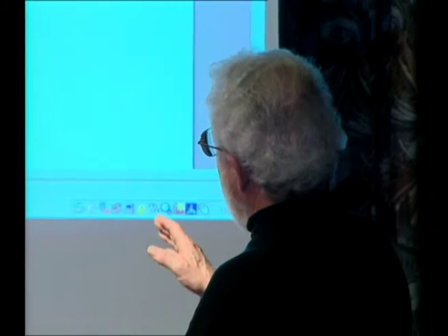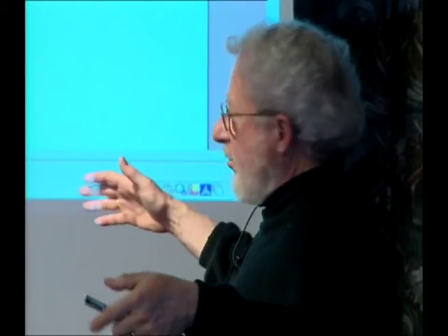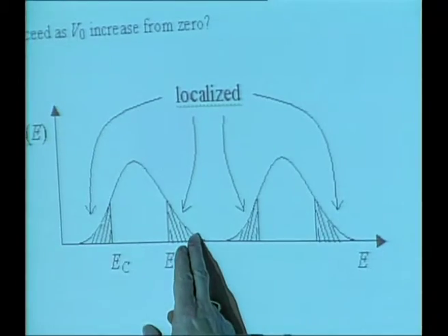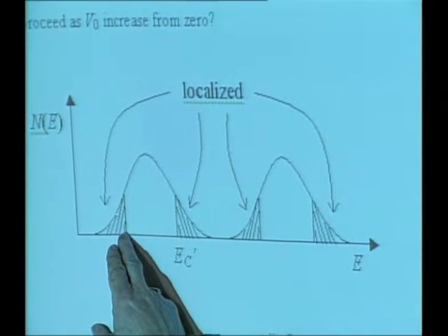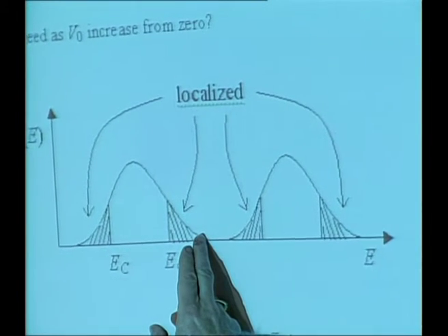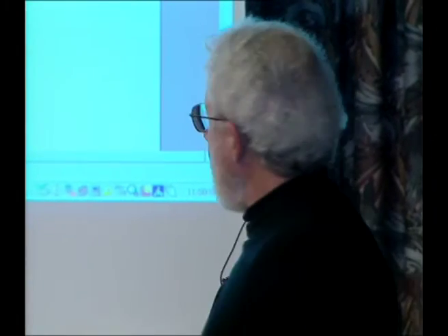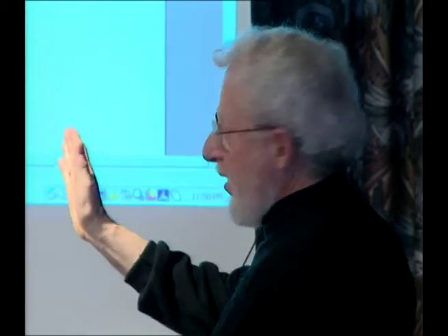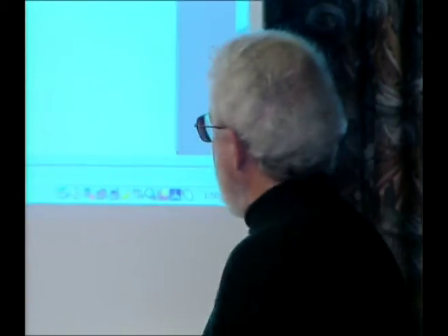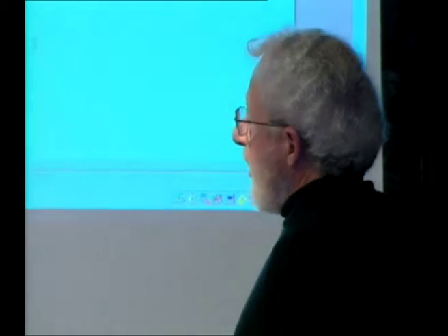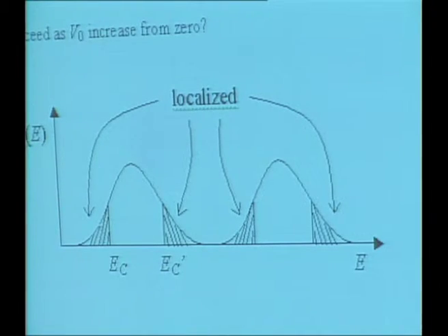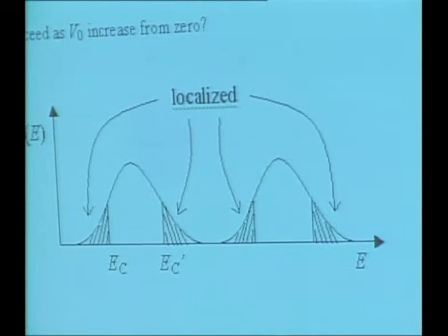And if the band is, if you start off with copper or something like a very broadband system, then, you know, this may not be very important. But if you start off with a single crystal of C60, what is it, potassium 3C60, which is a metal, but there's a very narrow band, then a little bit of disorder immediately will start to come in toward the center. And the critical issue, obviously, is in this picture here, are the states right at the Fermi level localized